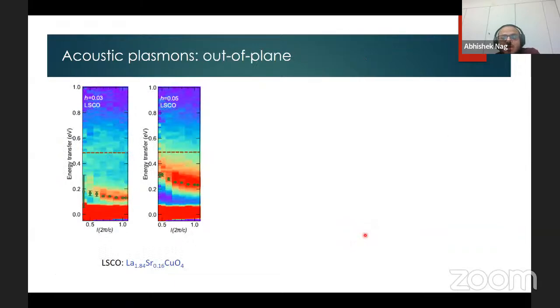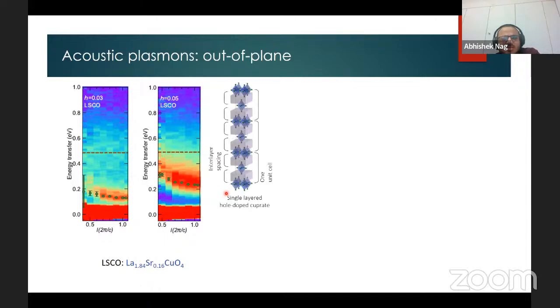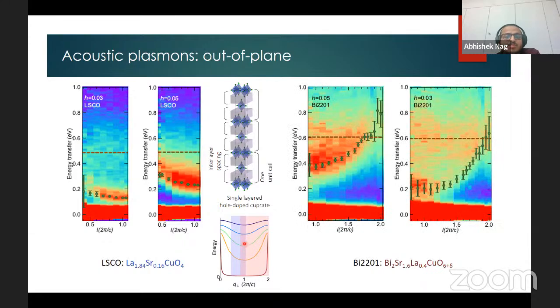So we probed along the out-of-plane directions, and we again see this dispersion of this peak in LSCO. In these single-layer cuprates, however, you have a copper-oxygen plane in the middle of your unit cell. So the periodicity in the out-of-plane direction is not at 1, but at 2. But with LSCO, we could probe only a very small region. So that's why we chose Bi2201 also, whose C-axis lattice parameter is almost twice that of LSCO, so that we could probe a much larger range of the momentum space.